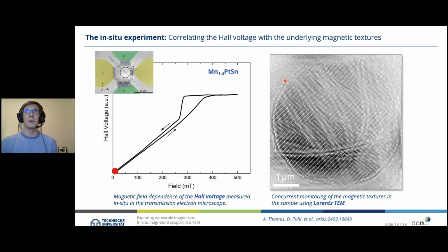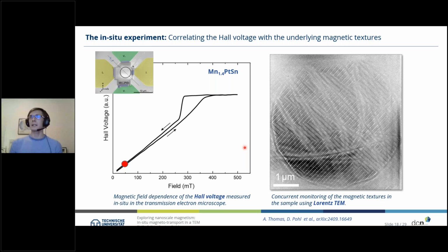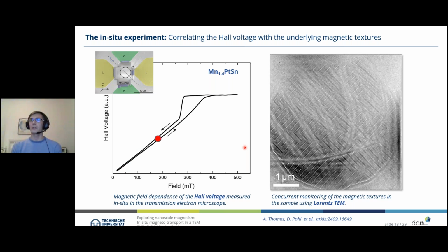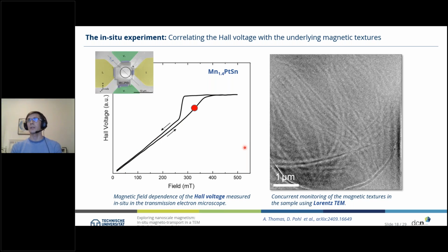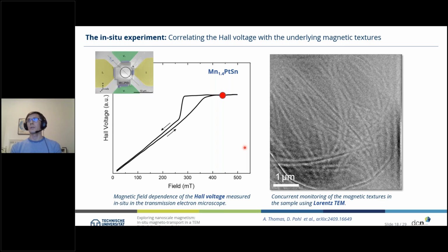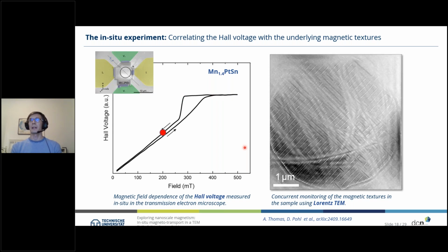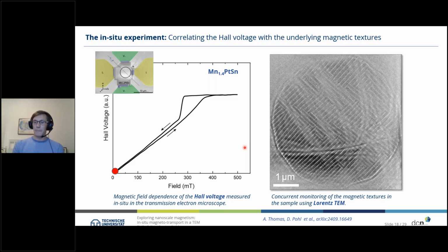So let me show the first experiment we've done on that sample, which is applying a magnetic field up to the saturation, measuring the Hall voltage, and just seeing how the sample reacts to different magnetic fields. And this is shown here on the right-hand side. I will run that video twice so that you get an impression. You see we are now in saturation. Nothing is changing anymore. And then the magnetic texture just pops up again. So let's run that again with a bit more detail.